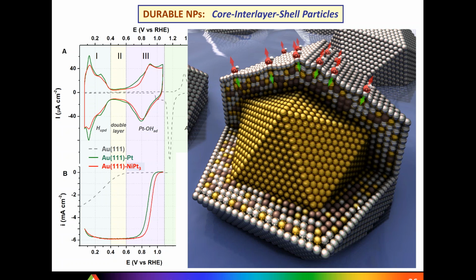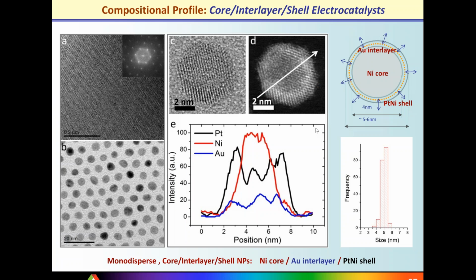type of shell. So not only are we using that knowledge of mixing gold with platinum in a very controlled way, but also we are introducing alloying components such as cobalt and nickel in this shell. And more recently, as I said, it's not only a gold shell, but actually a gold interlayer with a nickel core. So in order to make all of that more cost effective, we used a cheaper material such as nickel, and then we coat it with gold, and then we end up with several monolayers of platinum nickel shell. So what that brings is the following.